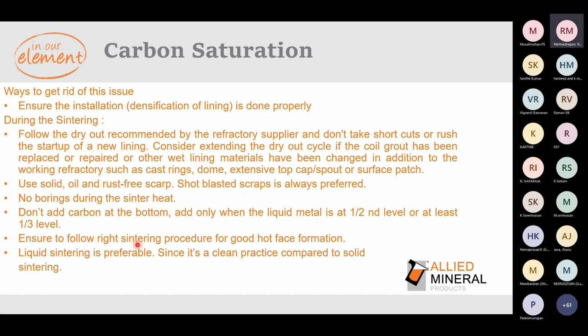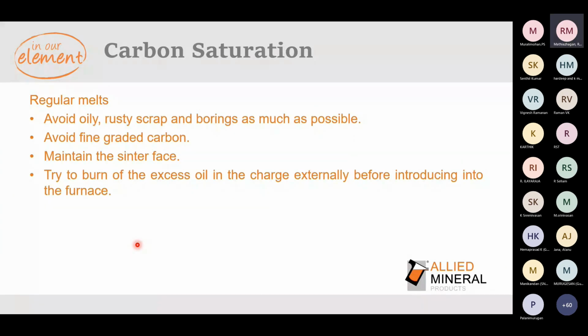Use only oil-free or rust-free scrap. Don't add carbon until the liquid metal is 50%, or at least 1/3 of the level. Follow the right sintering procedure for good hot face formation. As I said before, liquid sintering is preferable. And one more point I'd like to add here is to try to avoid adding fine grade carbon. Also, if you're trying to use oil scraps or oil borings, try to burn out the oil externally before it is introduced inside the furnace.